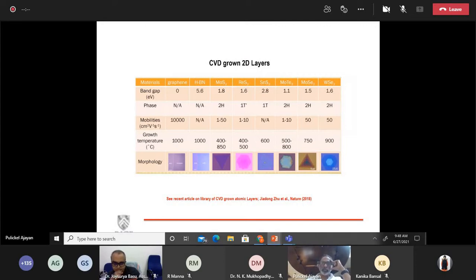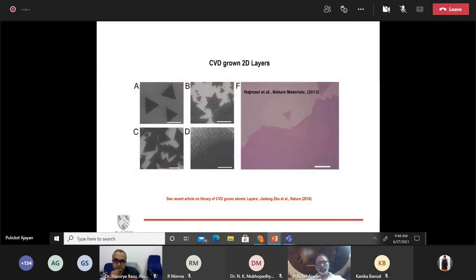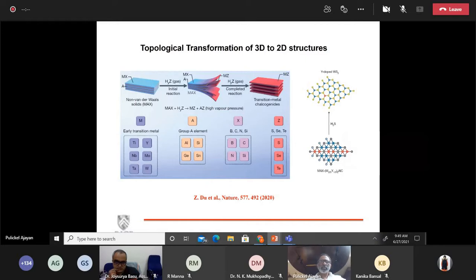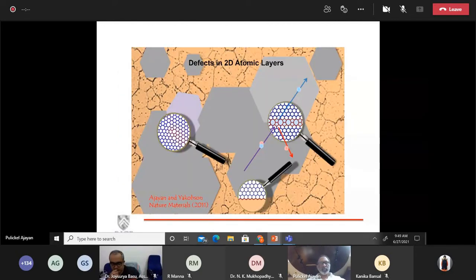Of course, exfoliation creates bulk amounts of these 2D layers, but if you want more controlled layer growth, you need to do vapor phase deposition or CVD growth. There are many techniques now that allow you to grow large areas of these 2D materials like molybdenum sulfides or graphene. And we were, in fact, one of the early pioneers in trying to grow these dichalcogenide materials from oxide precursors using chalcogenization in the vapor phase. And there are other new techniques that are emerging as well. Some work that we did with a group in China suggested that 3D MAX-like materials could be transformed to 2D structures using interaction with vapor phase gases like hydrogen sulfide. So there are multiple ways of creating these materials, either by vapor phase deposition or by exfoliation techniques.